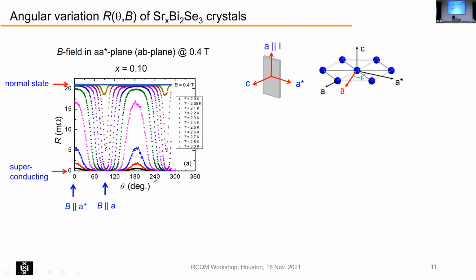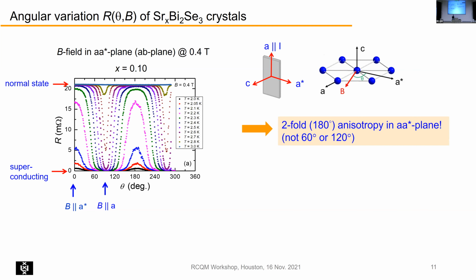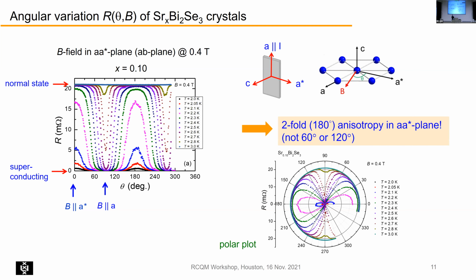But now, the strange point, of course, is that we would have expected a sixfold symmetry, 60 degrees or 120 degrees, but we see a twofold symmetry. That's really strange. That's really a puzzle. And that's obvious also if you plot the same data in a polar plot like this. This is for a current in the plane. I will also come to that in a moment.